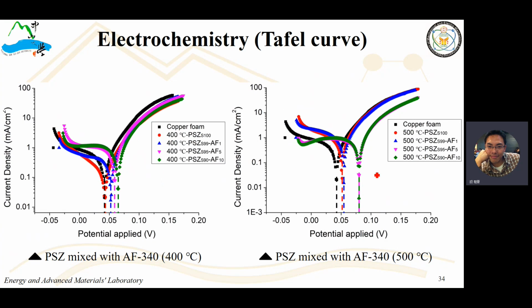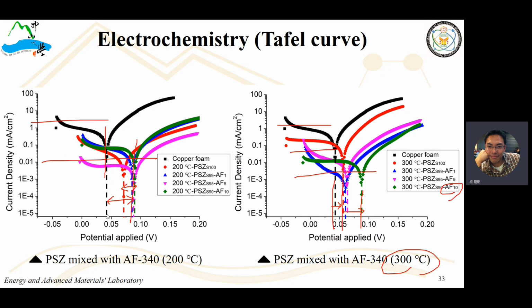And when the temperature is higher than 300, reaching 400 and 500, in fact, we cannot really tell the differences in between. We cannot really distinguish the corrosion potential and the corrosion current with the different fluorinated compound content. These Tafel curves already overlap. So this is direct evidence that the fluorinated compound decomposes above 300 Celsius. Even at 300 Celsius, we can figure out some clue that this fluorinated compound might begin to decompose.